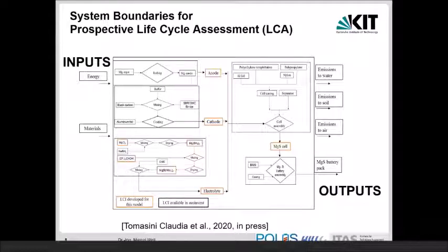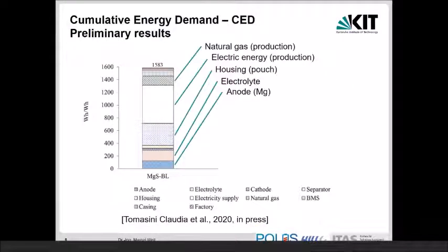And with the next slide, we see already the result of this study. And as I said, these are preliminary results. Here we showed a really simple environmental indicator, the cumulative energy demand, CED, and that counts all the different energy forms which are used for the production of the cell in this case. That means not only the energy, for instance electric energy, which goes into this system, but also maybe the coal which is used to produce the electric energy. That means the complete pre-chain of the energy provision.